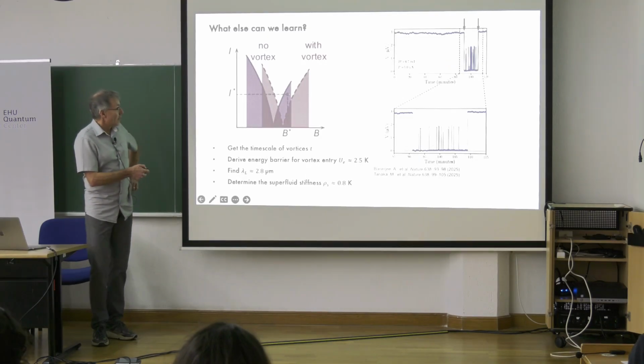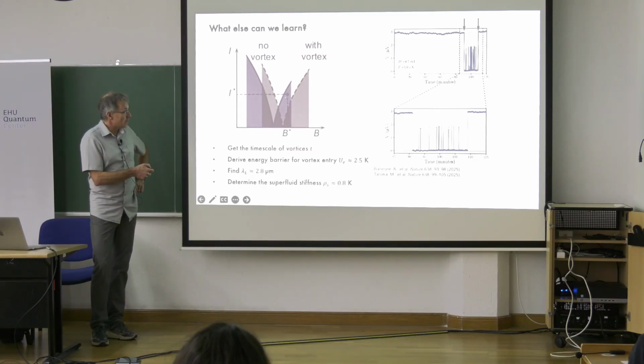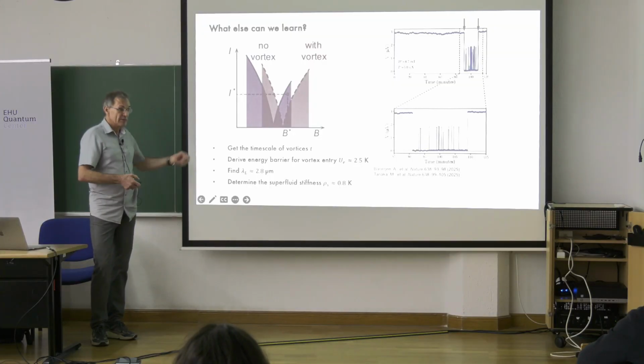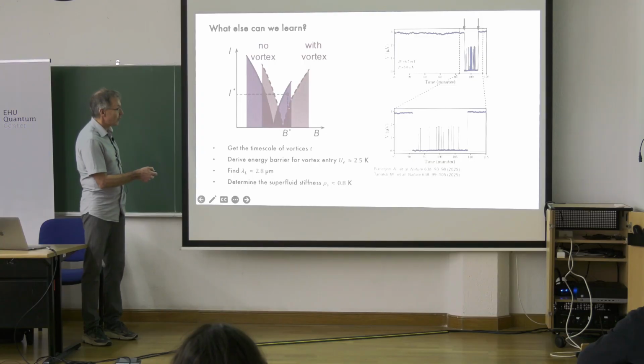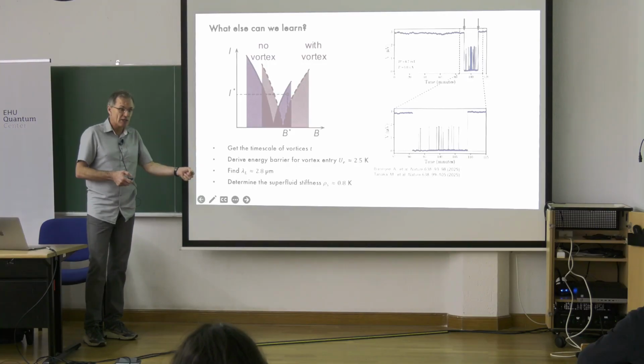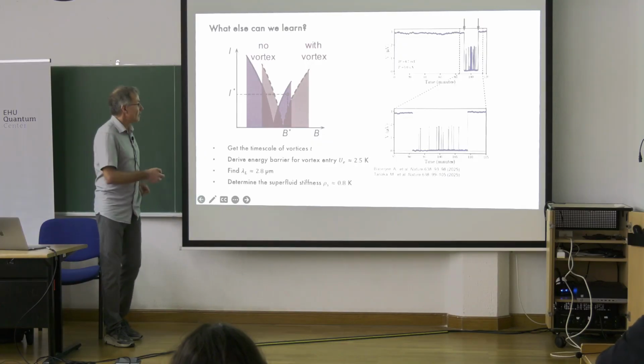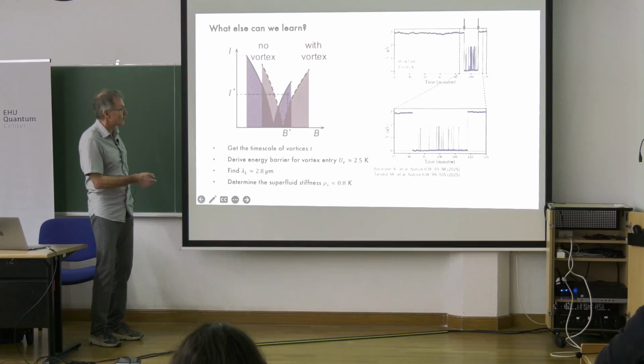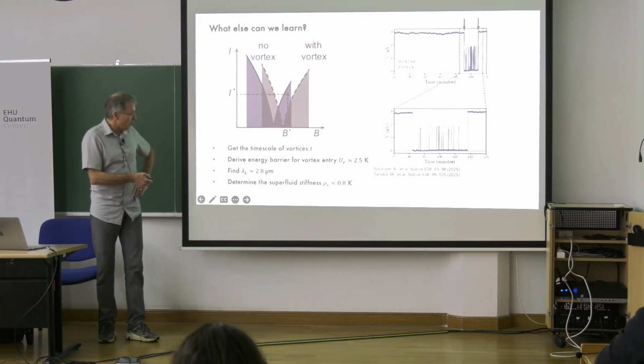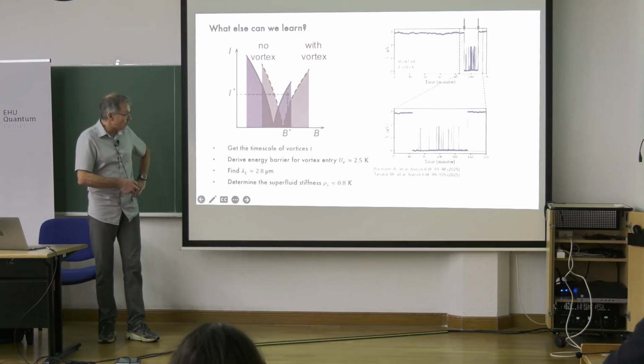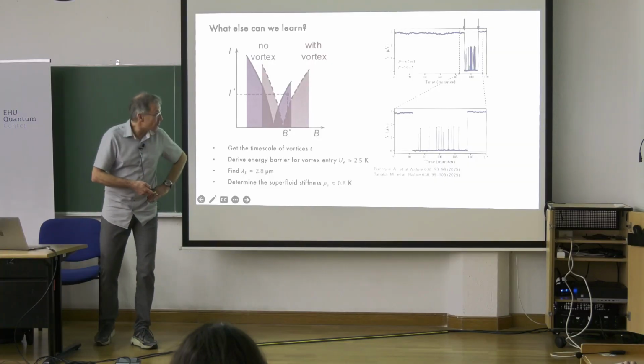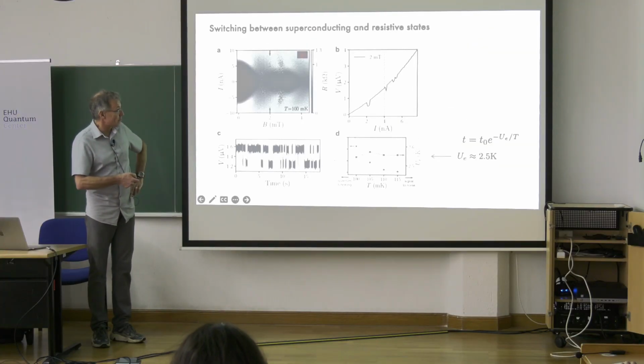What else can we know? Assume we put a current here, and we wait. And vortices, by thermal or quantum fluctuation, jump in and out. Then the critical current switches between this and that. And our current in one state is below critical, which means there should be no voltage, or above critical, which means there is voltage. So the voltage would oscillate together with vortices coming in and out. And from knowing how they go, we can derive the barrier. And from this barrier, we can find the superfluid stiffness. So that's how we then analyze the data.